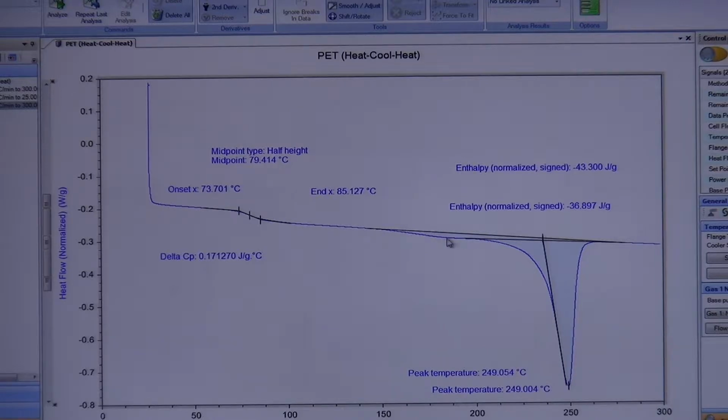So essentially this sliver here that we first left out are those smaller crystals that were formed as it was crystallizing, and now it has to be included as part of your full melting curve. So I did this just to show you that things like this can definitely happen, and you want to ask yourself those types of questions to make sure that you're doing the correct analysis and not leaving anything out. Okay?